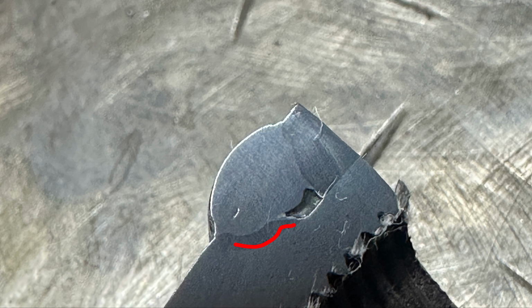One, this lack of fusion is 100% the whole length of the weld. There is not going to be like some 1/4 inch area that's like this. The whole weld is like this. When you look at all the previous welds, yeah, sure, some of them had defects, but they were probably only in a small section of it, not the whole weld. This is going to be the whole weld. You could have probably taken a toothpick and pushed it through there if I would have tried. Wish I would have. That would have made for a funny video.